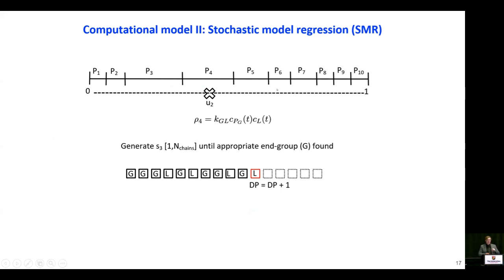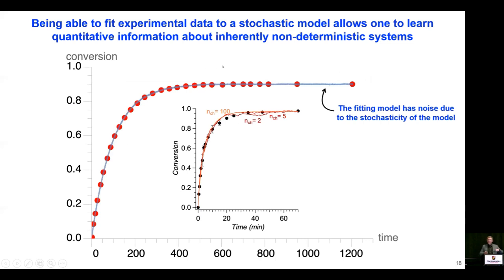We then increment the degree of polymerization with the lactide monomer. And then we update the time that was required for that event to definitely occur. So that is the Gillespie algorithm for simulating chemical kinetics probabilistically. And then we use that to fit numerically to our data. And so here's a sample fit of our stochastic model to experimental data.